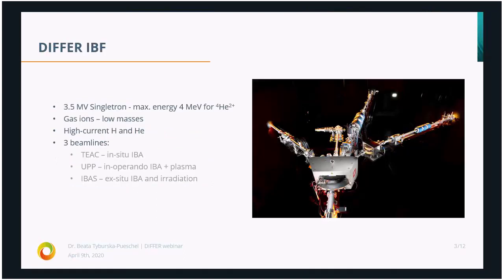So a few words about our ion beam facility. We are hosting a 3.5 megavolt Singletron accelerator from HVE, a Dutch company which produces those accelerators. There are in fact in the world two companies producing accelerators of this size. One is in the Netherlands, and the second one is called NEC in the US. And so we can produce a maximum of 4 mega electron volts for helium-2+, but usually we operate with energies of 2 to 3 mega electron volts.